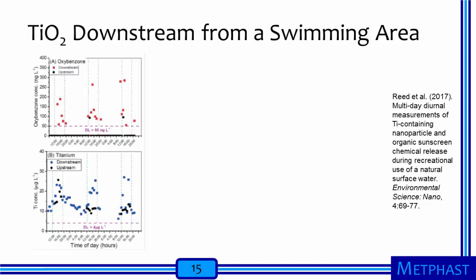Reed et al. studied the presence of sunscreen chemicals in surface water downstream from a recreational swimming area. They were able to identify higher concentrations of oxybenzone, an organic compound used to absorb UV radiation in some sunscreens, and titanium in waters downstream from the swimming area than in waters upstream from the swimming area. Both figures show concentration as a function of time. The black dots represent upstream concentrations, and the colored dots, red in the top figure for oxybenzone and blue in the bottom figure for titanium, represent the downstream concentrations. When swimming took place during the day, downstream concentrations were elevated.